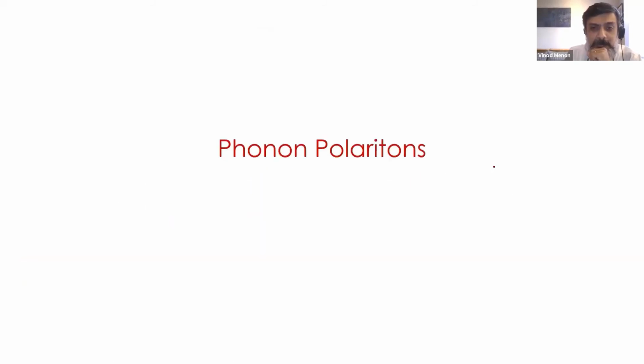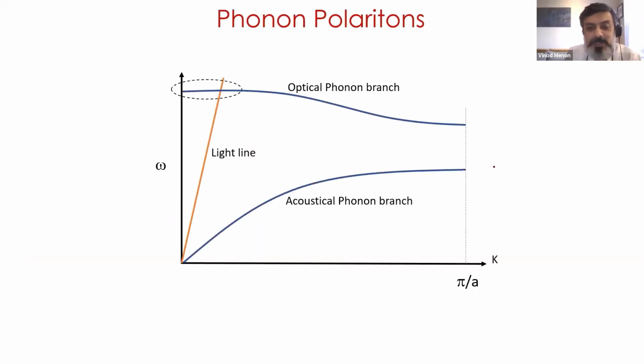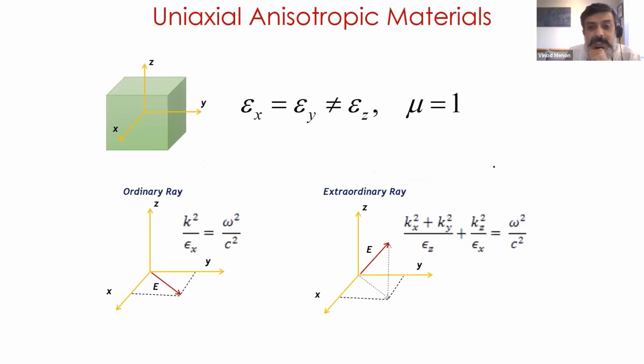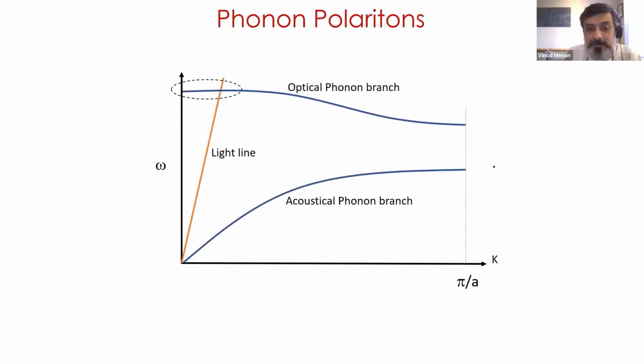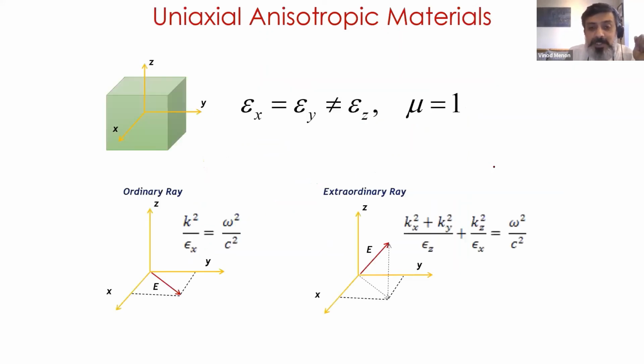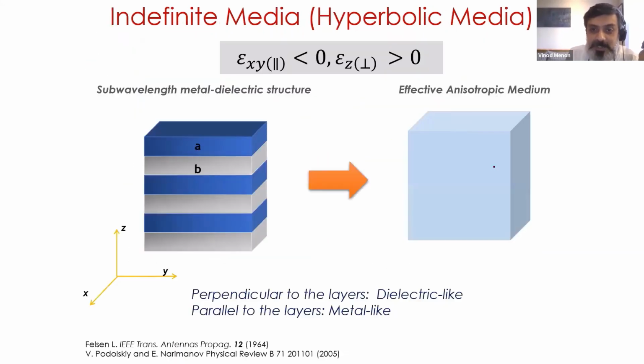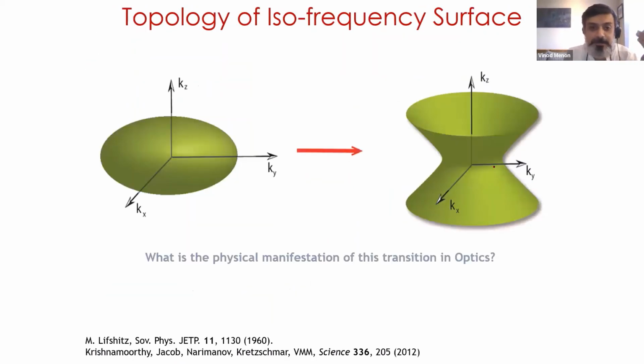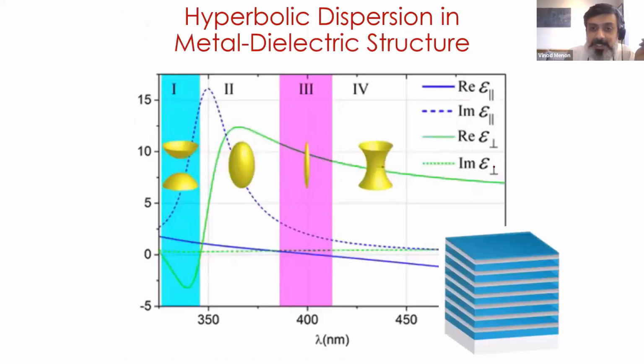So I think I'm going to briefly mention this, that this is not much work that we have done, but phonon polaritons are also very popular in these systems. Since I'm talking about polaritons and van der Waals materials, I just wanted to quickly mention that materials like hexagonal boron nitride host phonon polaritons, and these phonon polaritons have this property that they are anisotropic because the dielectric constants parallel and perpendicular in these materials have opposite signs. And so I'm going to just skip to this idea that if you take these materials and you look at their resonances at certain specific frequency, you will get this hyperbolic dispersion in this material, and they are naturally hyperbolic.